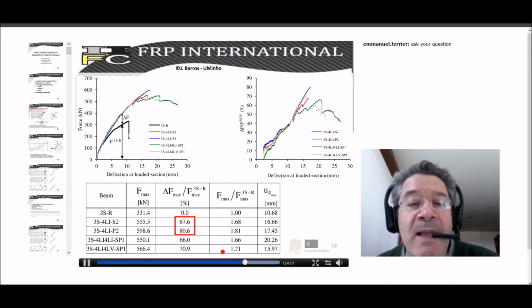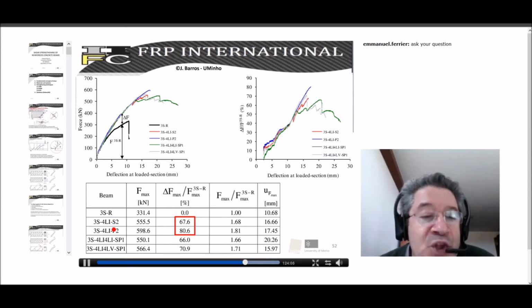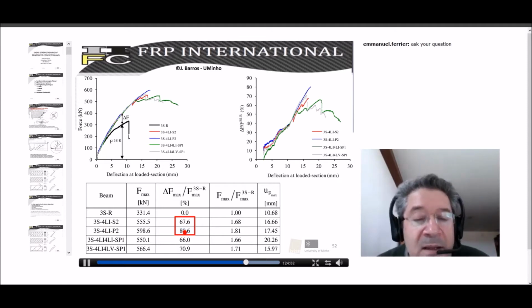And I only highlight the relevant aspects. Look, for instance, if I'm comparing these two beams, this is the force-deflection for all the beams, and I'm comparing the shear strength contribution. For the red beam, where we install 4 laminates at the surface, we obtain a shear strength effectiveness of about 68%, while when I install the same laminates but deeper in the groove, I obtain a shear strength effectiveness of 81%.